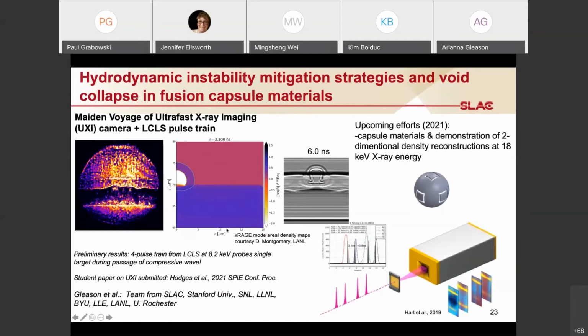Here's an X-ray areal density simulation from colleagues at Los Alamos National Lab. Once we're able to achieve much higher pressures, we can do a comparison to the density distribution as seen. Some of the really interesting features are at the edge or in the center here, these different curl-ups that have been discussed. Here's a synthetic radiograph of this at a certain time slice, and you can see some of these really cool circular curl features that develop. This is what we're looking for. This is the money shot that we eventually want to take and visualize in the data.